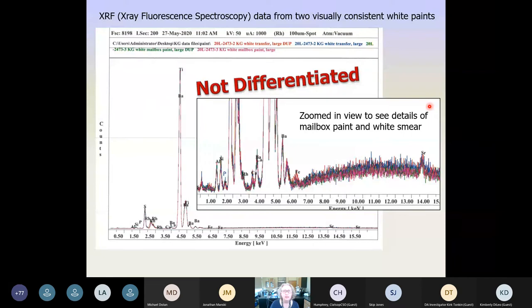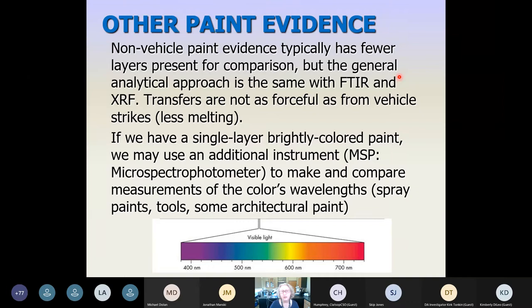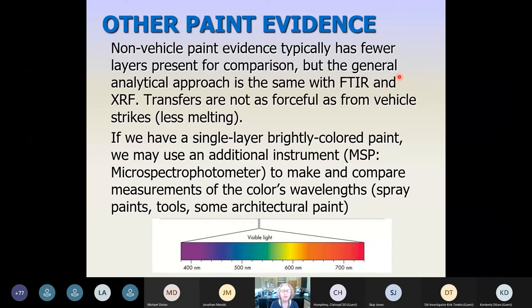Here's the XRF data for the same evidence — the paint from the mailbox and the paint from the smear on the suspect vehicle — overlaid between the two samples. Zooming in shows they nicely overlap and we cannot differentiate them via X-ray. One pitfall with something like a mailbox is it really doesn't have a layer structure — it's one layer of paint — and this is also true for many tools, painted door frames, and things like that. So in some situations if we have a brightly colored paint, we will take it to another instrument to do further analysis of the color and measure it more scientifically beyond what the naked eye can tell.